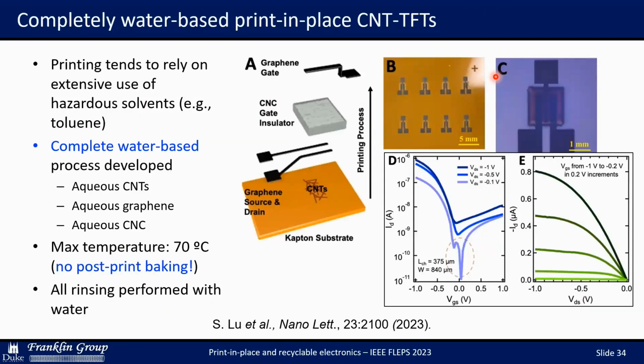So last of the results that I had mentioned in the title that came out just a few months ago is that technique with the all carbon-based inks and recyclability. We adapted it to be a fully aqueous process, meaning that we rely on nothing but water through the print steps. Now, if you've done work with nanomaterial-based inks, particularly carbon nanotubes, you would know this is a significant challenge because nanotubes, while they are able to be effectively dispersed with surfactants in water, do not print well into high-density films from that particular dispersion. So that was the challenge that we sought to overcome here so that we could use a process that did not rely on hazardous solvents. And you can check out the paper if you're interested in more about that work.